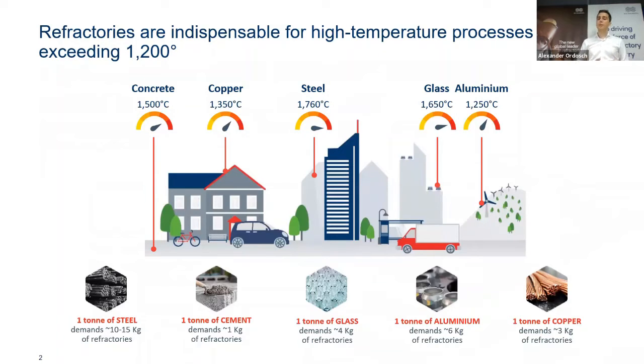Refractories are mineral-based products that have a very high melting temperature. And they are used in absolutely every application that involves temperatures higher than 800 degrees. So this starts with any furnace that you see, even a Swedish oven that you may have in your house has some refractories inside. But we at RHI Magnesita normally consider a refractory to be only a high-temperature product, so what we call refractory sustains temperatures above around 1200 degrees. Everything below is more like a lower grade part of the market.